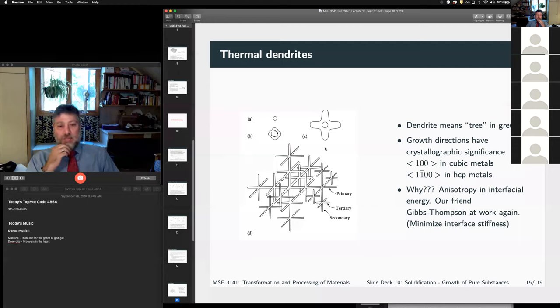Right? So you get a nucleus that forms these shapes. These tend to have a very strong crystallographic orientation with the growth directions, right? These dendrite arms tend to be the 100 directions for cubic metals, right? They're aligned with the A, B, and C crystallographic axes. The 1-bar 100 type directions in HCP metals, right?